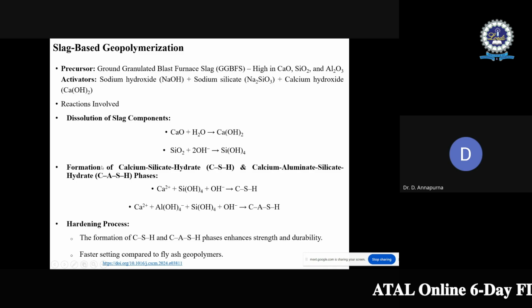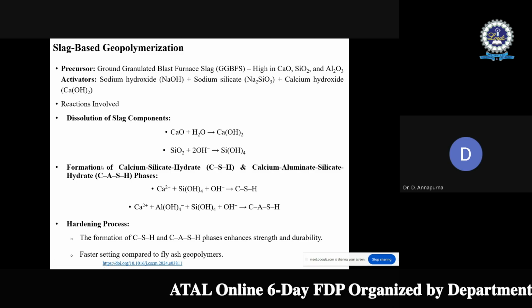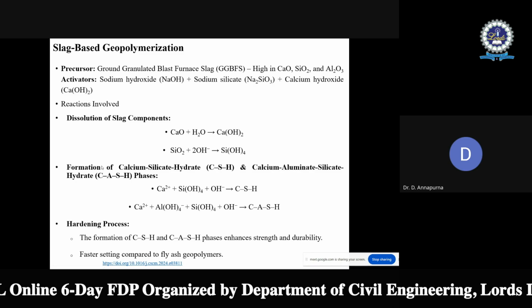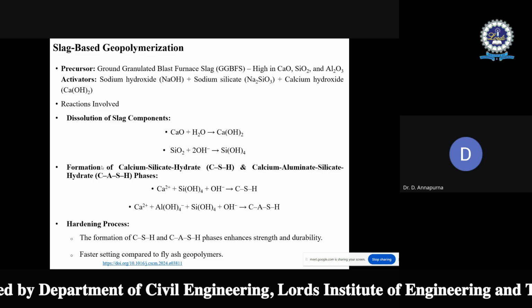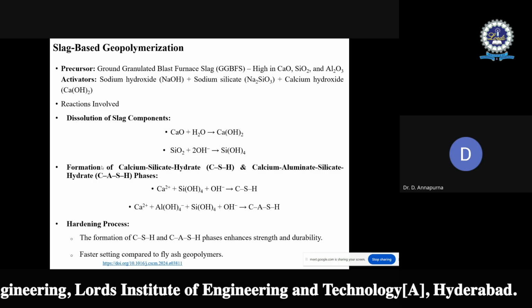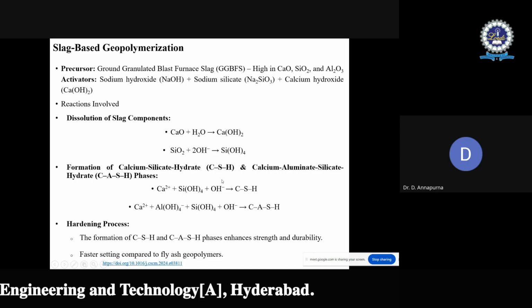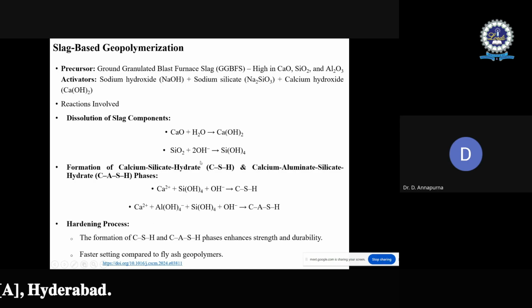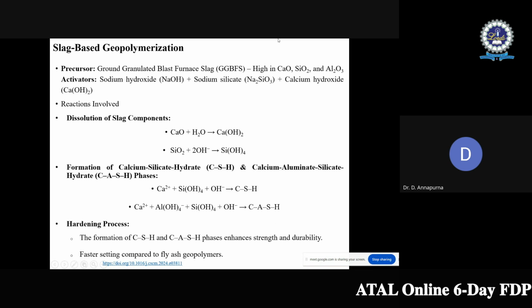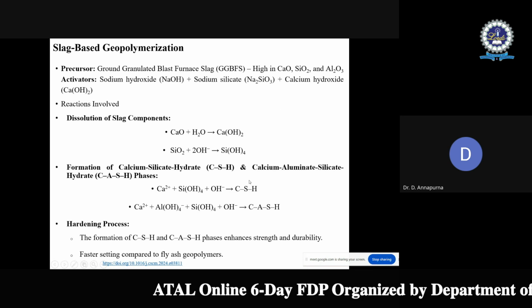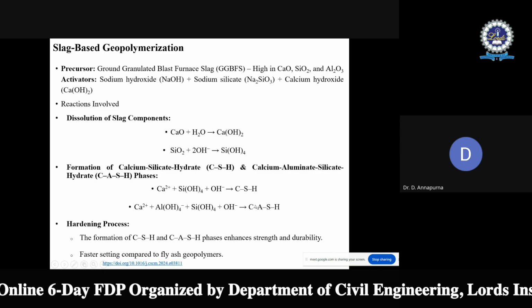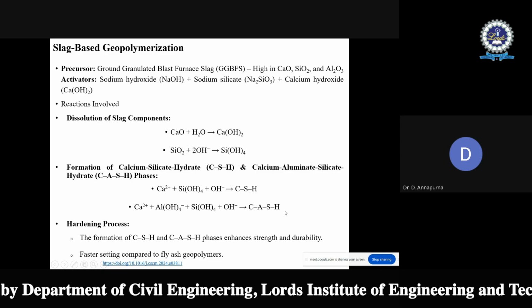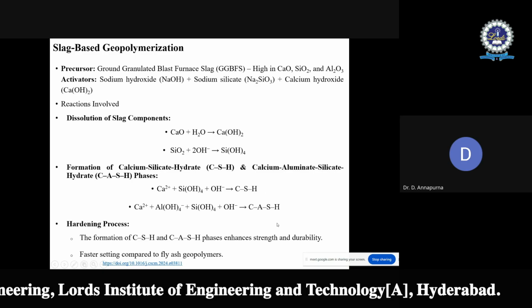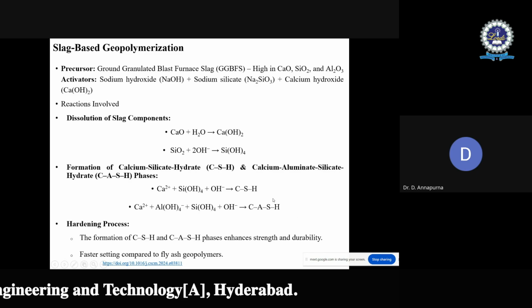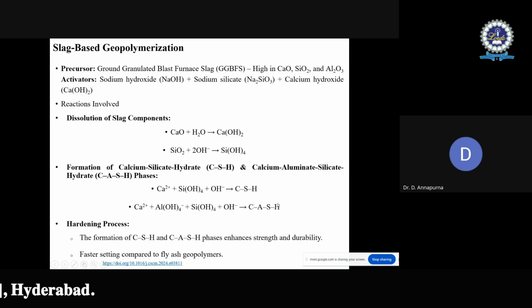Then comes the polymerization. In the earlier stage, it gives NASH, sodium aluminate silicate hydrate gel. But here, since it is rich in calcium, it is going to give calcium silicate hydrate first. Then that calcium silicate hydrate is going to form calcium aluminate silicate hydrate, because it is equally rich in aluminate. The very important aspect of this slag-based geopolymerization process is the setting of geopolymer concrete.